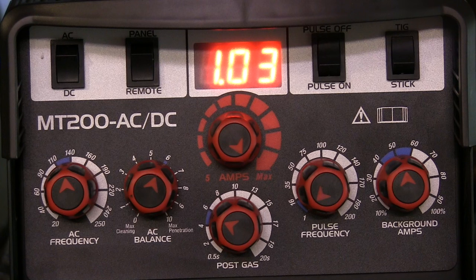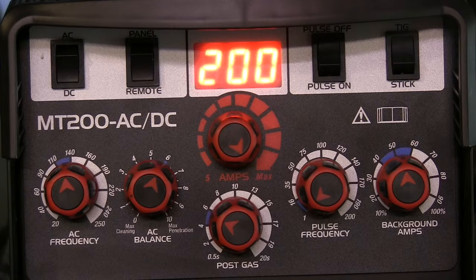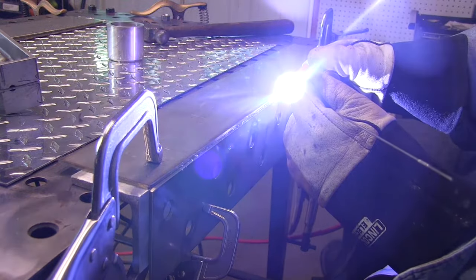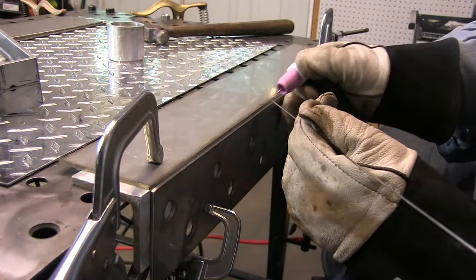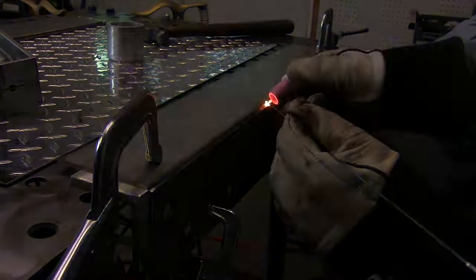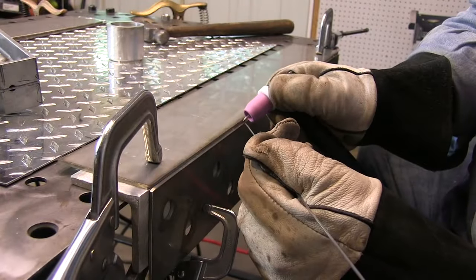I'm going to go hotter than normal just for tacking. I got the machine pegged out at 200 amps here and I'm going to prop the cup and then blast it really quickly with a tack. I don't want to sneak up on it. I want to hit it and get it.